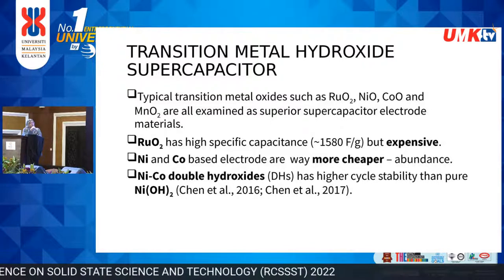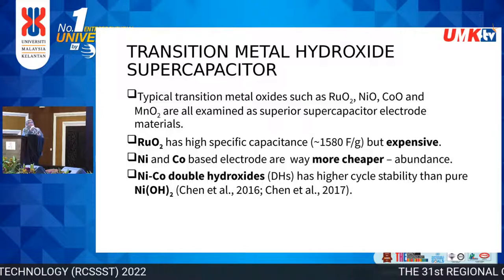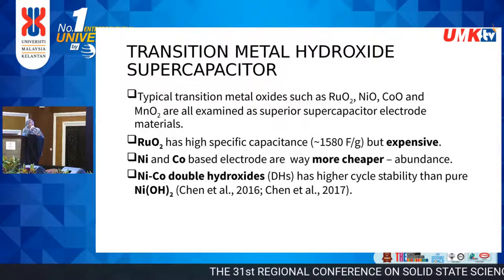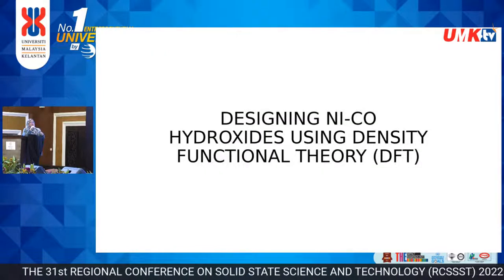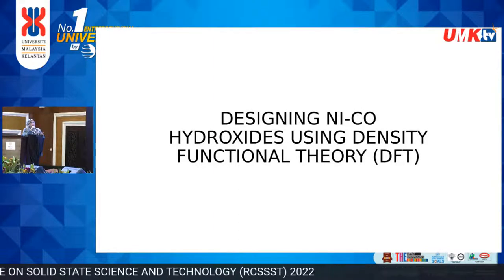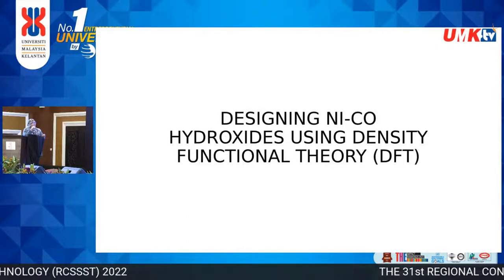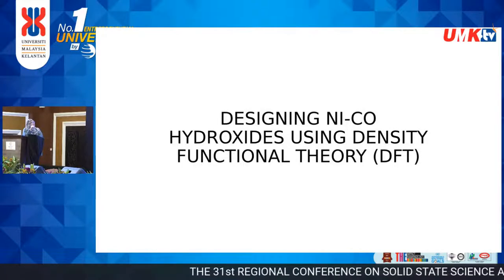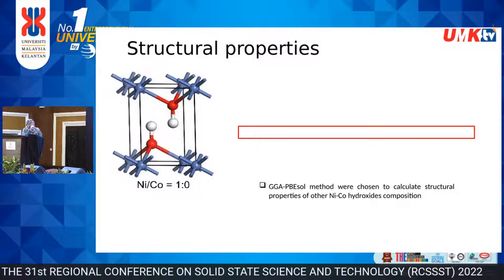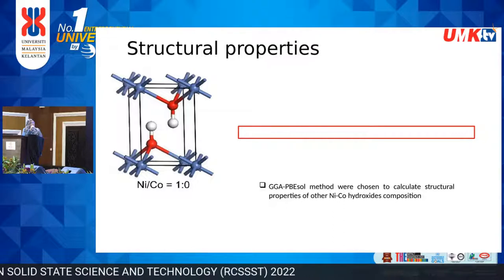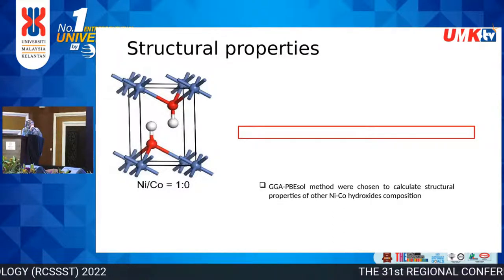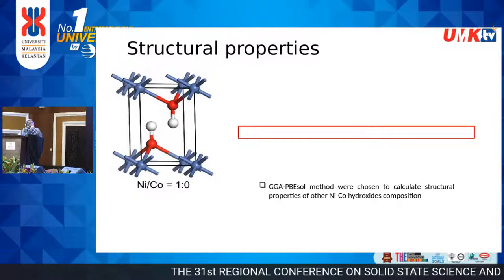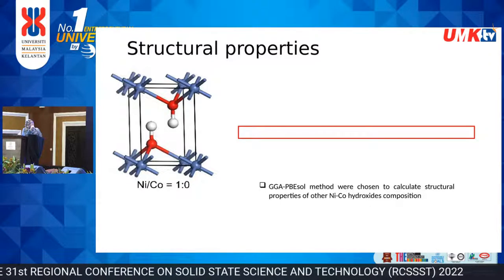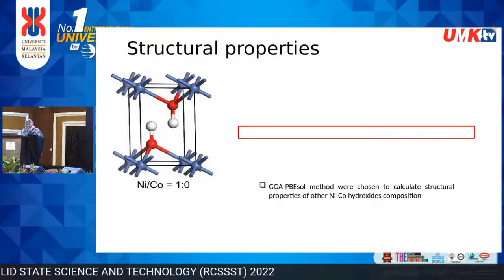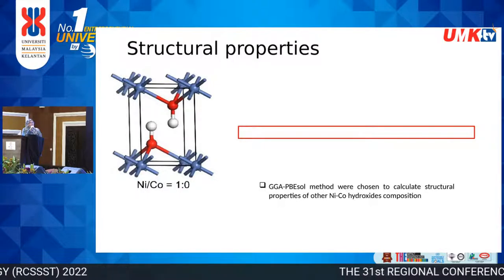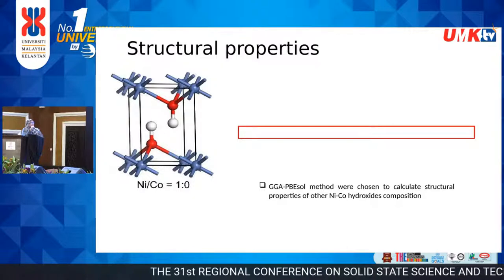First, in designing the nickel cobalt hydroxide supercapacitor, we use density functional theory to estimate the best ratio of nickel cobalt hydroxide that can give the best performance to our supercapacitor. This is the structural properties of nickel hydroxide. We used several methods of DFT, and we can see that the GGA PBEsol method is the closest to the experimental value, which is 3.143 for 37.539 volume. So this method is chosen to calculate other properties of the nickel cobalt hydroxide compositions.